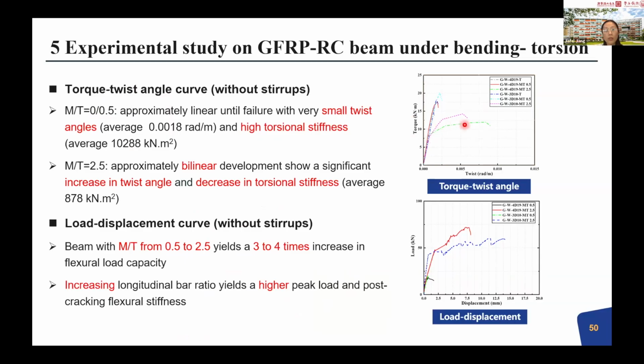And for the behavior, here is the torque twist angle, and we are finding that with the increase of bending, the torsional twist deformability will increase, but the capacity will decrease. And looking at the flexural behavior, here is the figure for the center load and the deflection in the center. We also find similar behavior to the flexural behavior, but flatter, I mean in the deformability. But also when the stirrup and longitudinal bars increase, they have a significant effect on the flexural capacity, which is similar to that observed in flexural design.